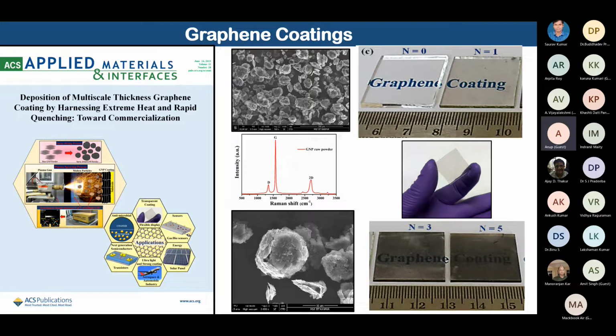Okay. Thank you. So now let me show you our other work. We discussed the graphene powder, but now we are going to show you the graphene coating, right? Now graphene coating means, you can see here, this was a different work which has been published, again, in a good journal. And in this, on the top side, you can see the graphene powder which is spray dried, meaning we really cannot spray the pristine graphene. So what did we do? We made balls of agglomerates of the graphene, and on this we did the initial characterization. You can see at the bottom, at high magnification, one particular spherical ball of the graphene.